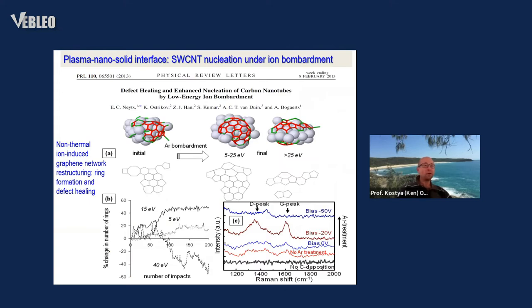Plasma interactions with carbon nanotubes and the catalyst particles start from the very initial point when these nickel atoms accept some carbon atoms and some initial carbon hexagonal sp2 carbon networks form on the surface of these particles, and then they shape up, and then they extend and form carbon nanotubes.